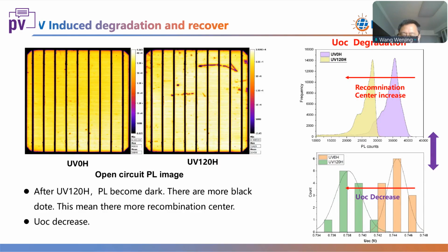We analyze the PL of this kind of solar cell before and after UV light. After UV for 120 hours, the PL becomes dark. There are more black dots, which means there's more recombination. And at the same time, we find the VOC decreases.